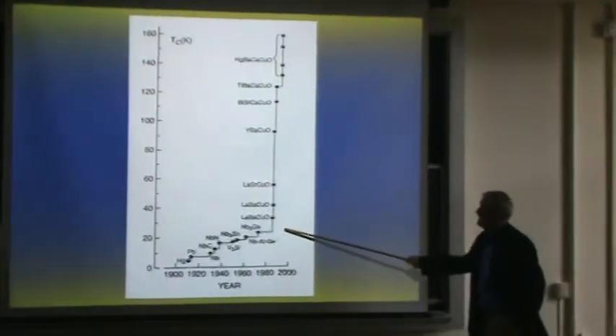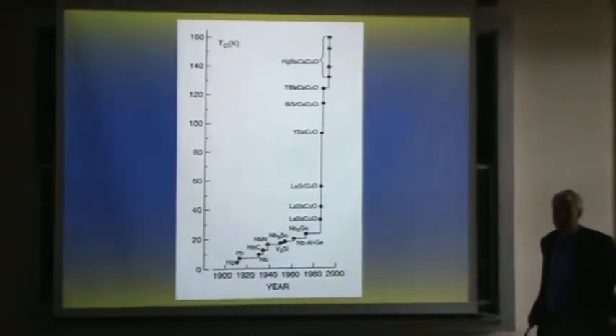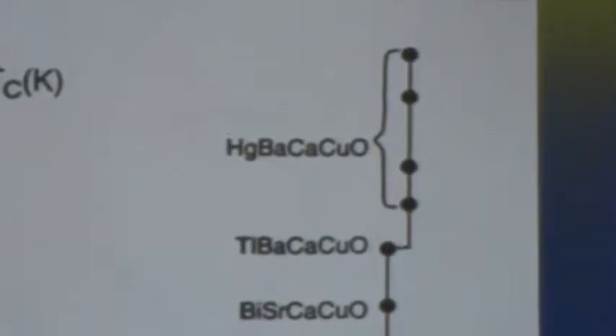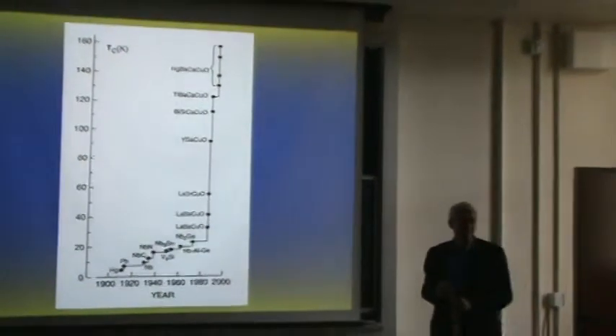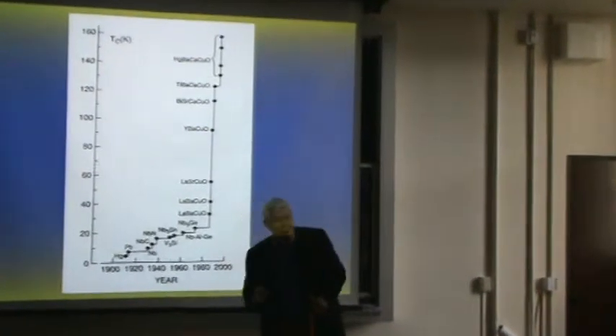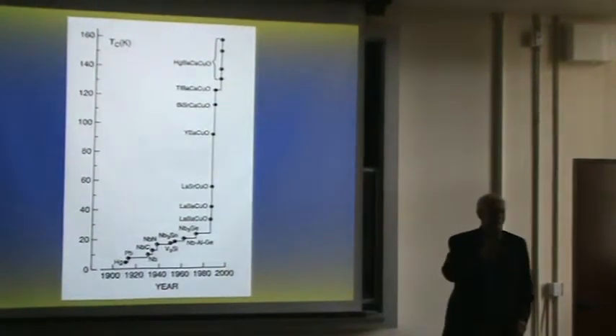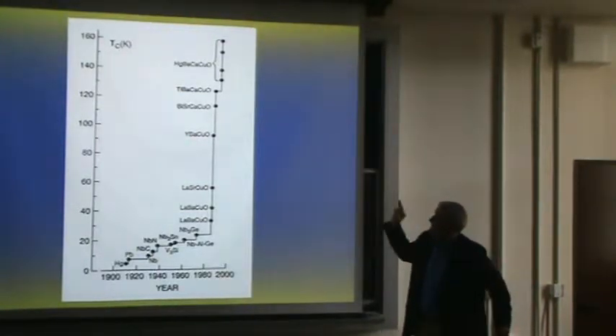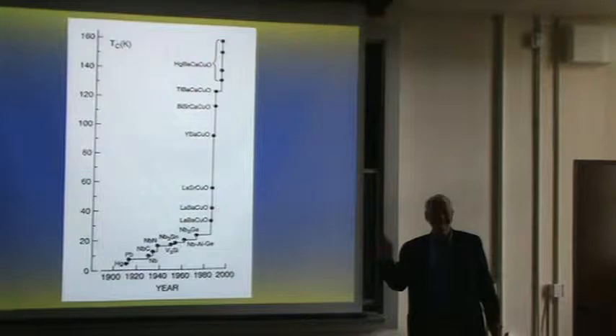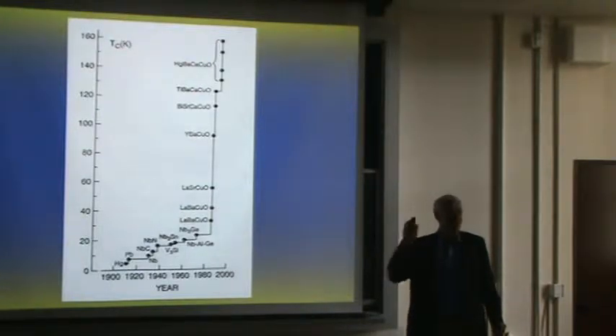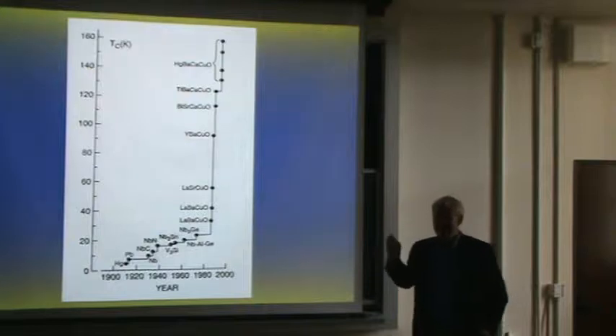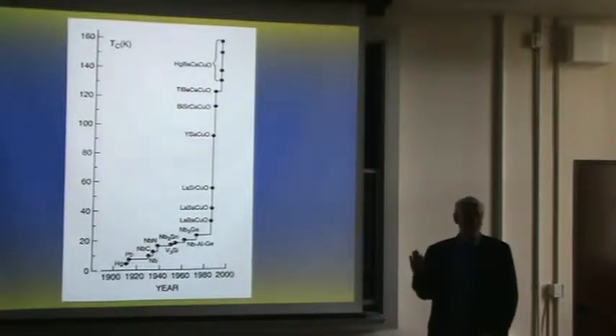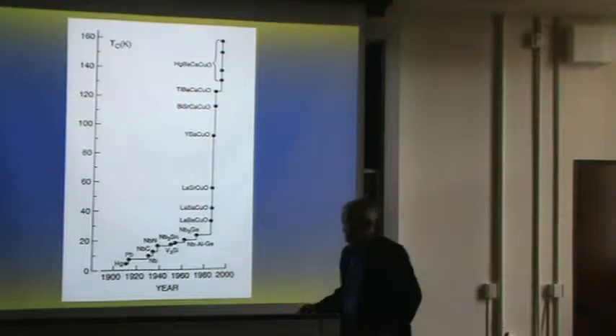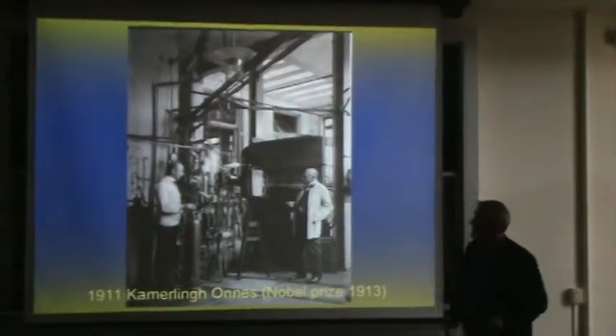In any case, then there was a discovery of some new materials based on copper and oxygen. Very unexpected, even more unexpected than you could ever imagine, and I'll explain why. And this got all the way up under pressure to above 160 degrees Kelvin, which still sets the record. It's pretty remarkable. But I think more senior people here would agree, even if instead of being 160, it was 16, these materials would still be as remarkable in terms of trying to understand the physics. The fact that they're superconductors at all is remarkable, much less superconducting at record high temperature. And I'll try to explain why that's the case.